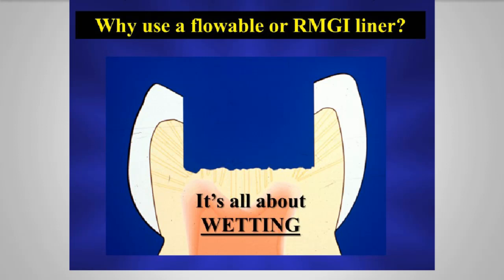So it seems to make some empirical sense if we use a low modulus or very flowable material like a resin-modified glass ionomer liner or a flowable composite, that we can better wet and get into all those little interfaces. Then we can place our more heavily filled materials on top of that. And there's another potential reason that flowables and resin-modified glass ionomers may have a clinical benefit, although this is somewhat controversial. It has to do with modulus of elasticity.